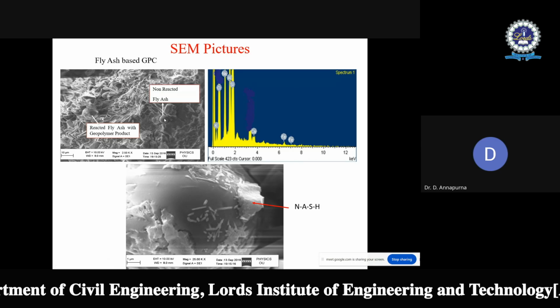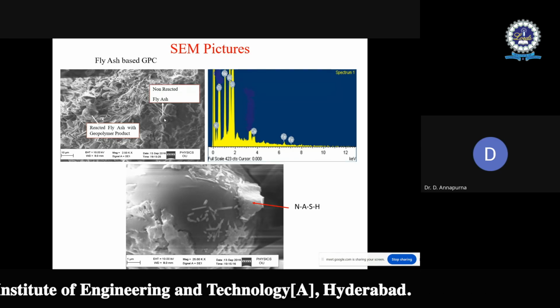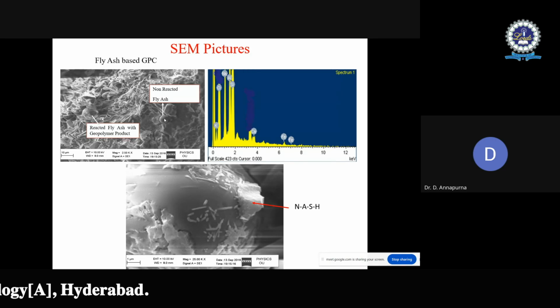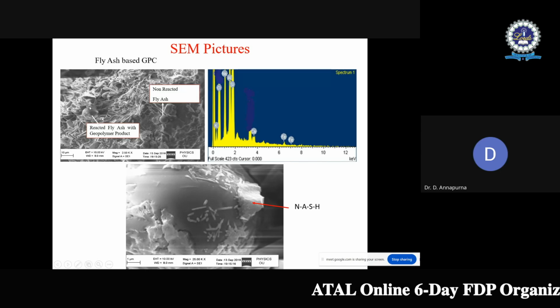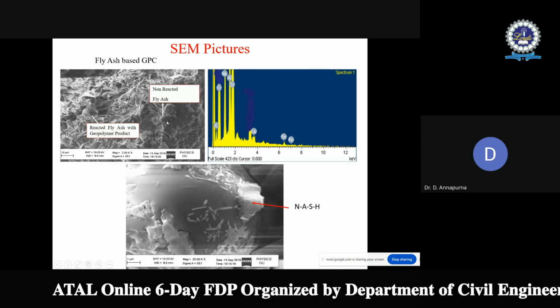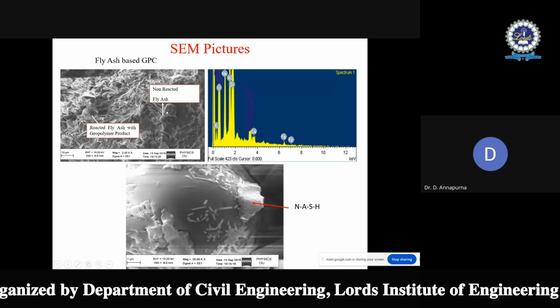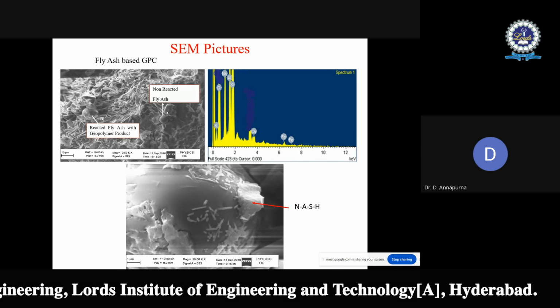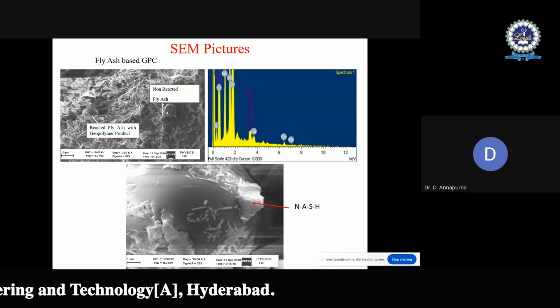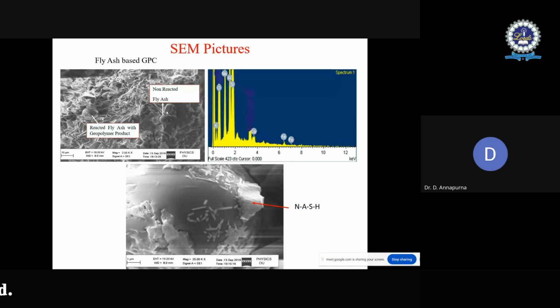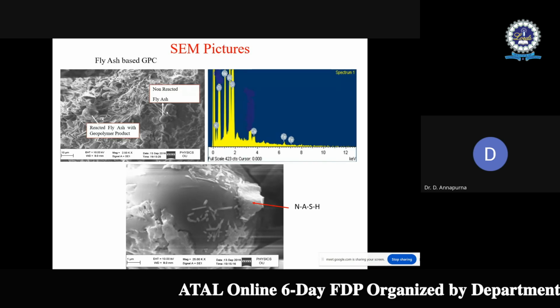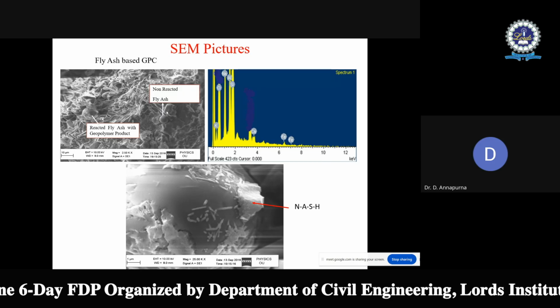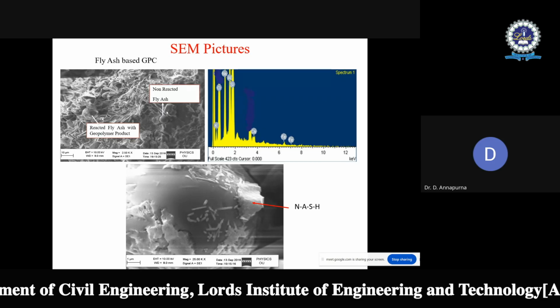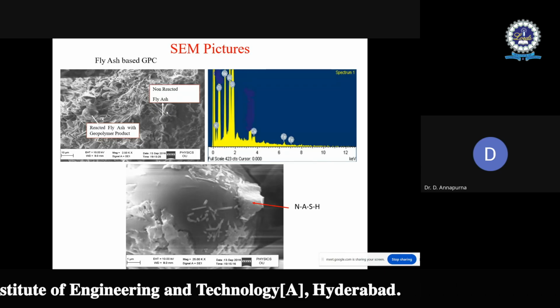So here it is clearly seen through the SEM pics on the fly ash based geopolymer concrete that a little amount of reaction products is observed on the fly ash. More non-reacted fly ash is seen. That means after 28 days, much fly ash is available which is non-reactive. When we discussed fly ash based geopolymer concrete, we understood that it takes much time to react, slow setting, etc. The reason is validated through SEM pics.